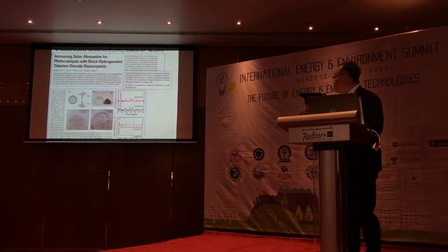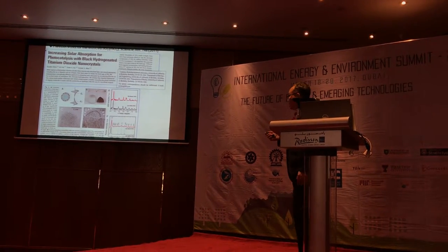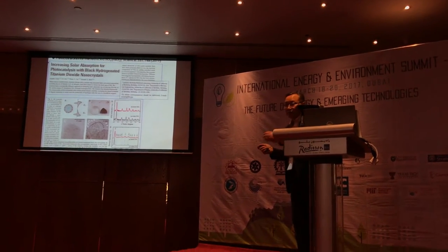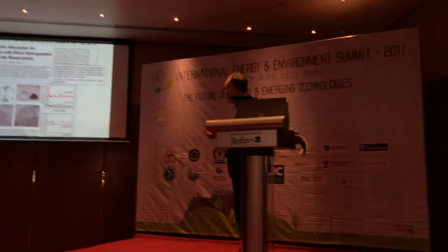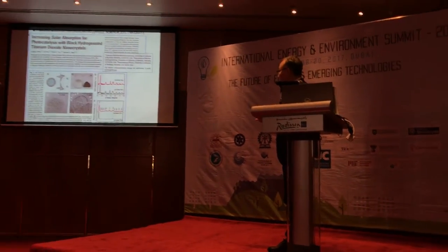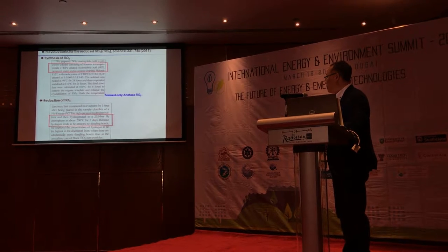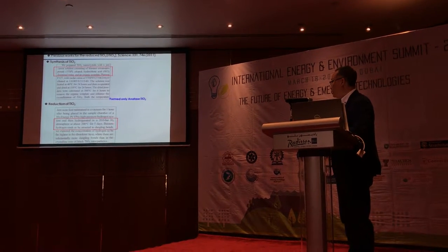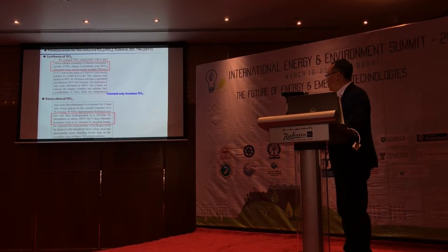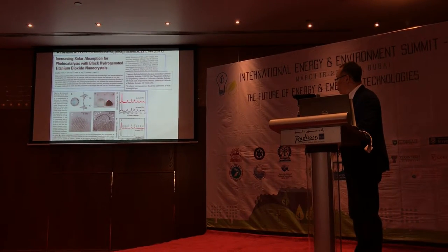This is the science paper from the Mao group. The paper shows that this is the titanium dioxide material, and the science paper describes the making of black titanium dioxide. They are using a 20 bar hydrogen atmosphere at about 200 degrees Celsius for 5 days, and eventually they got this kind of black titanium dioxide.